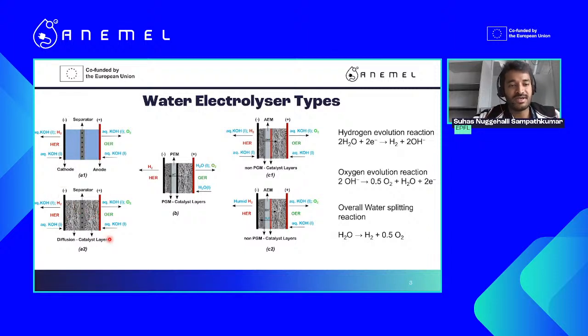But these separators have drawbacks because they have pores in them, and there are chances that the hydrogen can cross over to the oxygen side, which results in a safety issue, because concentrated hydrogen and oxygen is an explosive mixture. To eliminate that, a different technology which conducts protons was invented in the 1980s or 1960s, if I'm not wrong, which is called proton exchange membrane electrolyzers, using platinum group metal catalysts. And these produce dry hydrogen on one side, while allowing for pure water feed on the oxygen side. So this also functions as an electrolyzer, quite a good one.